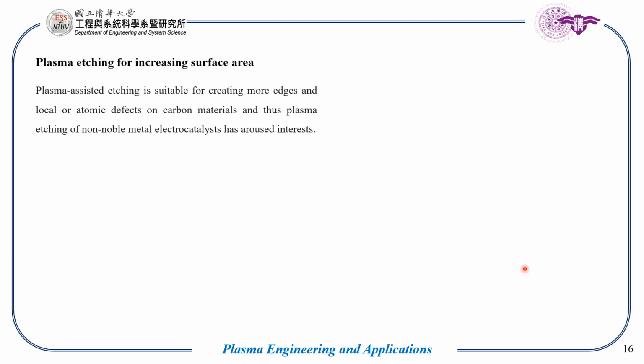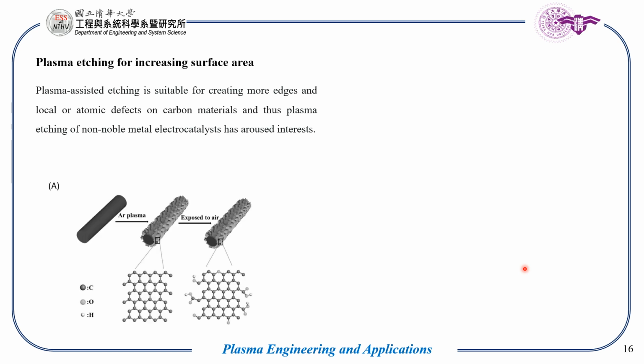Now we will talk about, apart from creating defect deficiency, how plasma etching can increase the surface area. Plasma assisted etching is suitable for creating more active edges, and these active sites act as a source of many reactions, and these active sites become more available towards the hydrogen and oxygen evolution in these areas.